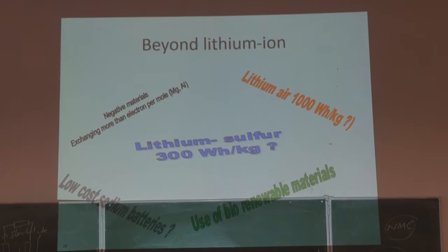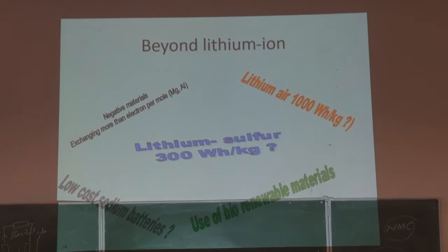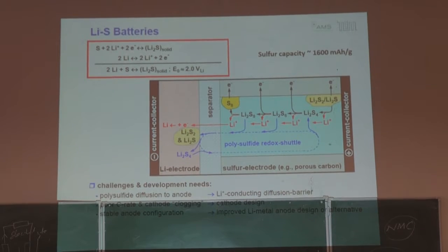That's why they want to go for that conversion part, not the intercalation part. There you have sulfur or oxygen as a cathode. This is why people use the lithium sulfur battery. In this case, again, we test it with lithium. When this happens, your capacity should be about 1600, because this is a conversion, right?